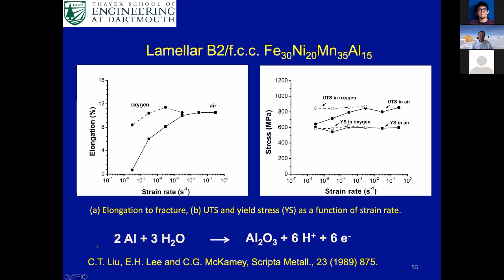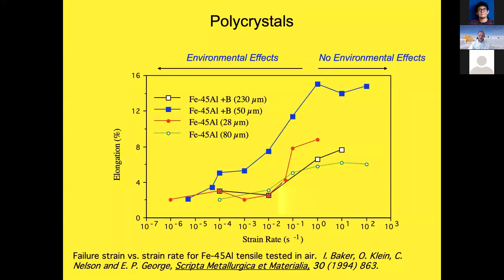Liu and co-workers proposed a mechanism for the environmental embrittlement of iron aluminide. The water vapor attacks the aluminum, forms aluminum oxide, and then releases atomic hydrogen. This atomic hydrogen then diffuses into the material. If you're doing a high strain rate test, there isn't time for hydrogen to diffuse into the crack tips. But if you're doing a slow strain rate test, then the hydrogen can diffuse in and lead to fracture.